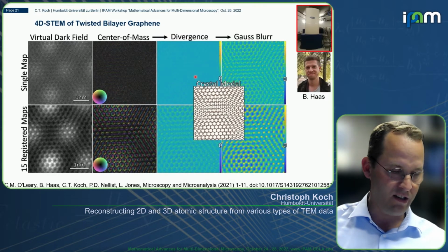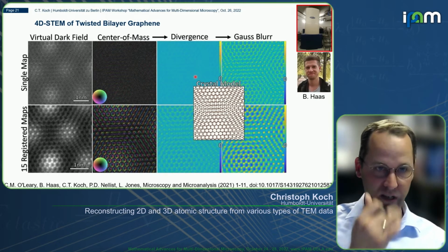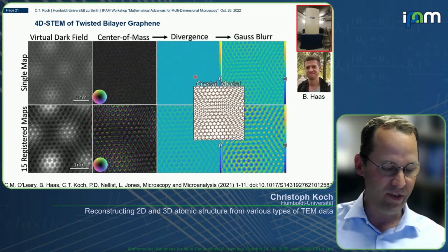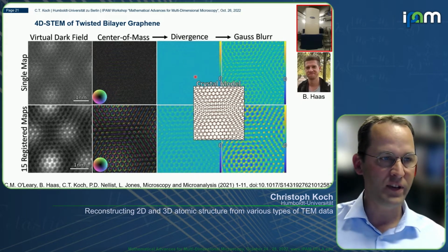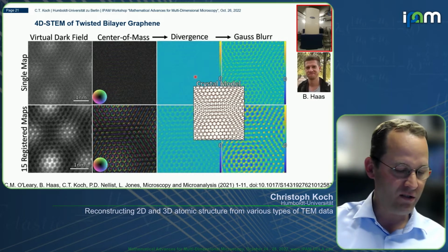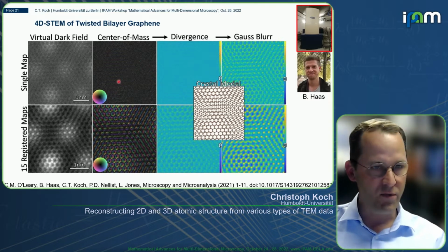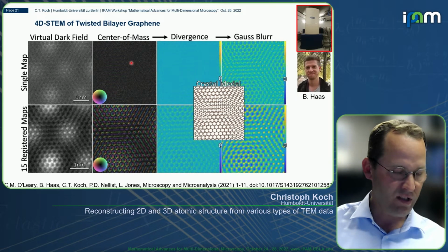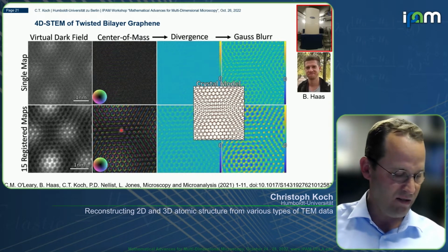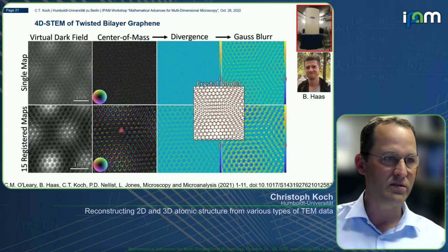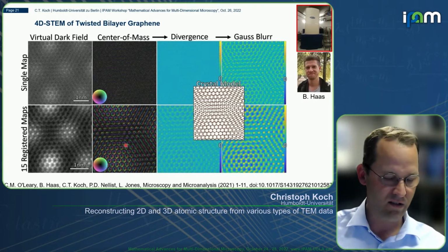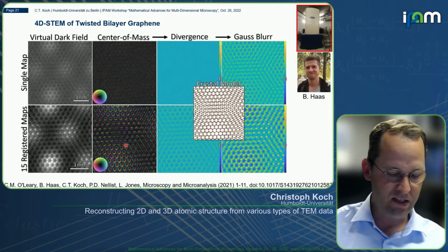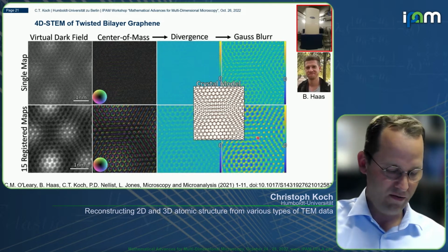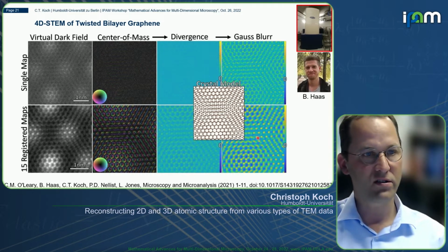And this is just something, when you go down in voltage, you get more strong scattering from thin materials. For example, this is the twisted bilayer of graphene, where when you scan very fast, you don't actually record so much information. The information is quite noisy, but you can then acquire multiple scans and really improve the signal so that even for this bilayer of graphene, with a simple center of mass analysis of your data, you can really get very nice atomic resolution information about local atomic scale electric fields. And of course, if you take the divergence, you get something that is proportional to the charge density of this material, or the projected charge density.